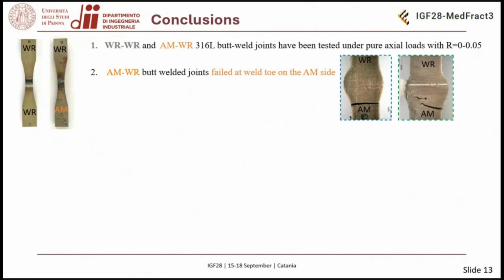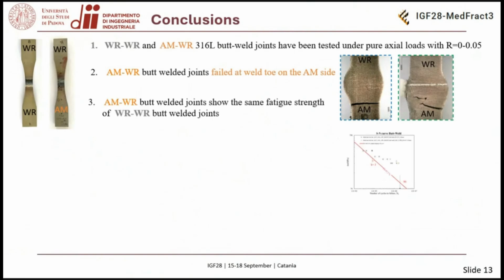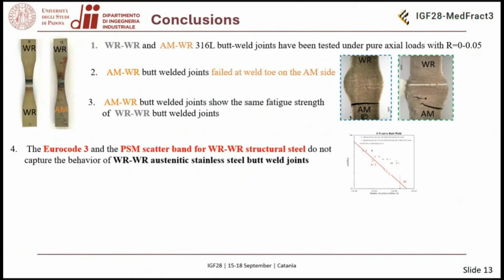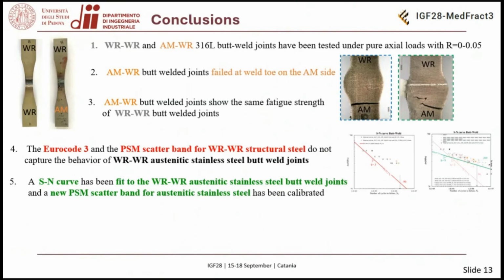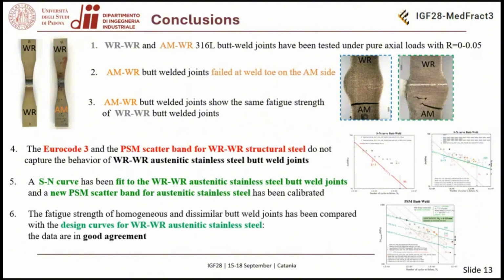We observed that failure occurs at the weld toe due to the notch effect, also in the case of joints with an AM part. And in this case, failure occurs at the weld toe on the AM side. We observed that the fatigue strength of joints with an AM part is similar to that of joints that are traditionally manufactured, but it differs from the prediction of the Eurocode 3 curve. However, our data are in good agreement with the literature's and also with a design curve and a design scatter band defined for austenitic stainless steel traditionally manufactured welded joints.